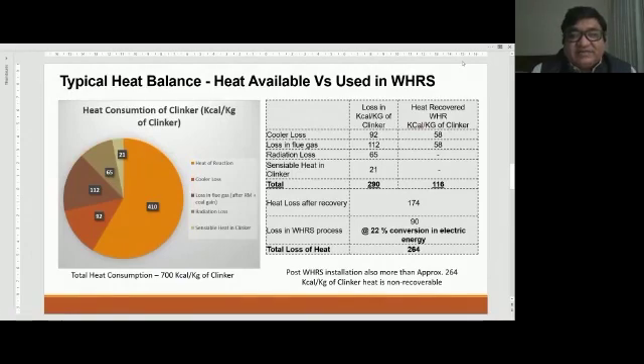If you see the right hand side, the losses are almost 290 kilocalories in our process. And if we install WHR, especially on the cooler and preheater flue gases, we can capture only 58 and 58 theoretically, which equals about 116 kilocalories per kg of clinker. So it means 174 kilocalories is still going out, which cannot be recovered. But interestingly, even though the recovery rate in the WHR process is not very high compared to other power generation technology, at only 22%, you can still see that we can achieve significant power from this heat.